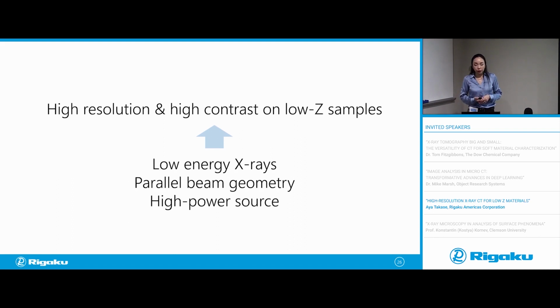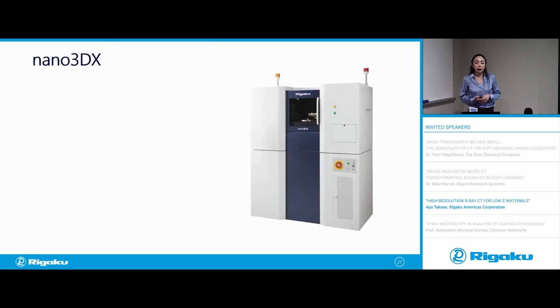Now, one of the systems that I have with a low energy, high power, parallel beam setup is the Nano 3DX. And this is a Rigaku system. And of course, I'm using the Nano 3DX as an example because I work for Rigaku. But most of the CT systems you see in the market are usually using the cone beam geometry for a very good reason. It's very versatile and it's relatively inexpensive to cover a wide range of resolution and field of view.